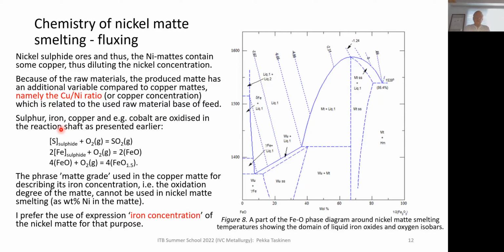So many older scientific papers on nickel smelting only talk about the concentration of nickel in the matte, but they don't pay attention to copper, which is actually a diluting component in nickel mattes, and thus decreases its activity when copper is present at high concentrations.